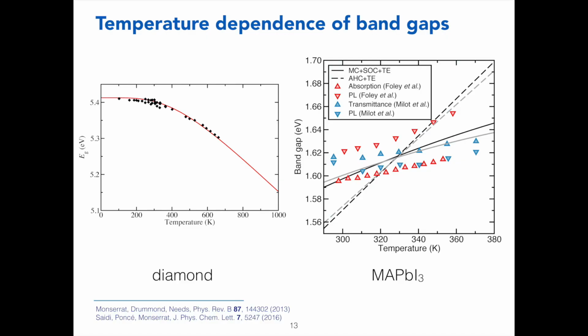And then I'm showing two theories. So the first one is the dashed line, and that corresponds to using perturbative methods to incorporate the electron-phonon interaction. And you can see that in these more complex materials, those perturbative methods don't actually do very well. They severely overestimate the change in the band gap with temperature.